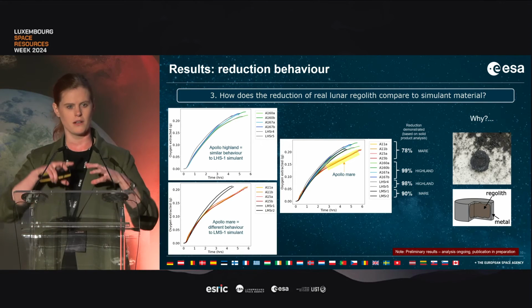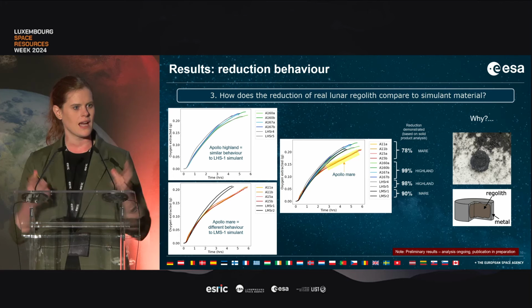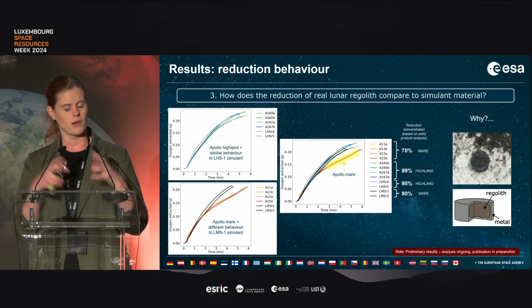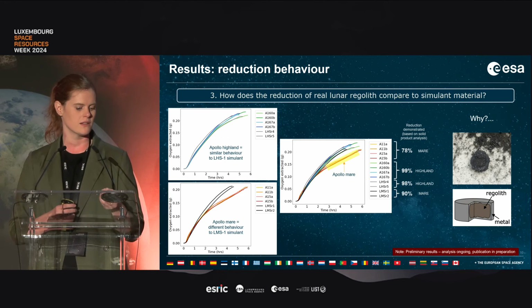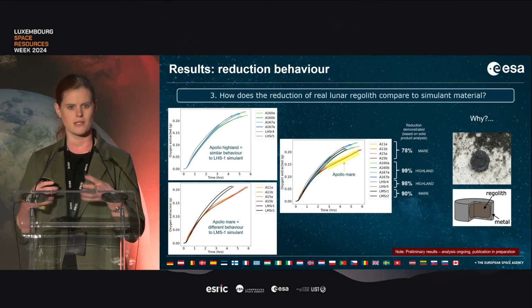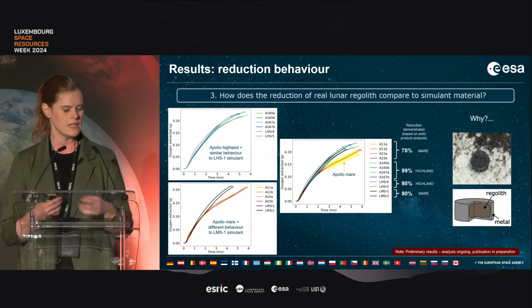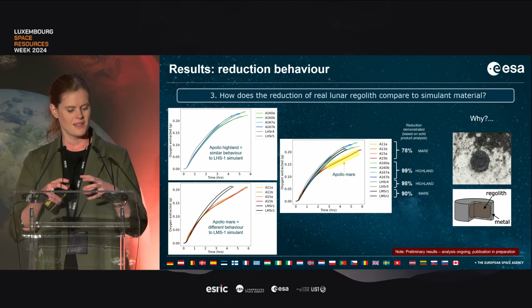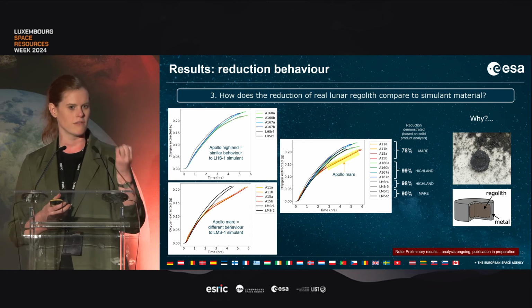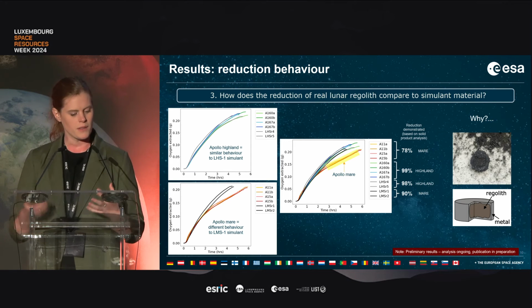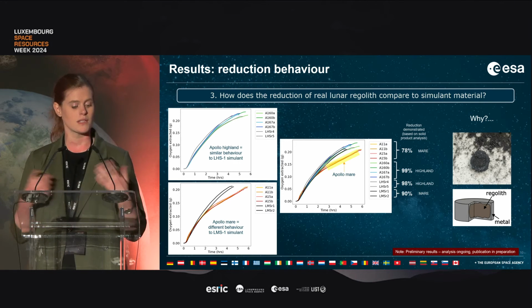But it appears to be related to the fact that the Mare material forms this kind of metallic outer shell, and then it really blocks access to the interior material. It's kind of hard to see from the picture there, but it was easier to see when processing the material visually. There was this outside core and then an unreduced inner core. And so that might be relating to the compositional differences between the materials. So how much calcium is being uptaken and forming intermediates, and maybe that volume expansion is blocking pores.